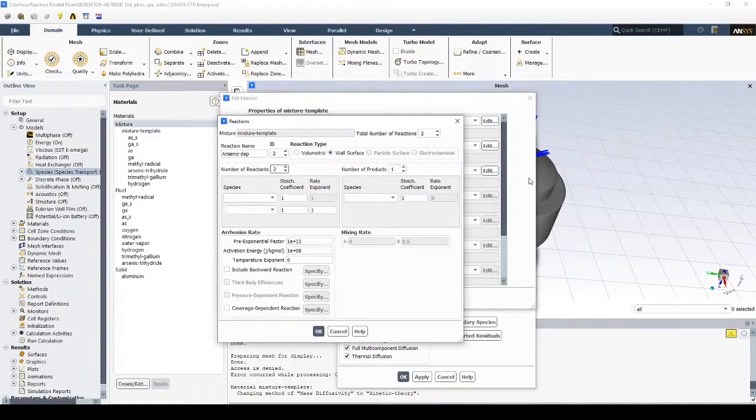Same as before, this is a basic two-equation reaction with two reactants and three products. Here we have GaMe3, and it's going to react with my arsenic site species, and it'll produce some arsenic being deposited on the surface. We'll have a gallium site created, and then some CH3 is also created here, and actually apparently there will be 3 of these. So let's put this information in again.